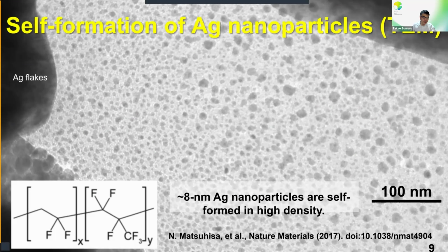So this view graph shows you the ink formulation. So we add the silver flake with a typical dimension of 2 to 3 micron among the fluorinated copolymer, adding the surfactant and organic solvent, mixing together, printing once and annealing at 150 degrees Celsius. So when we observe the cross-section of the printed elastic conductor, we eventually realize the silver nanoparticles are naturally formed and uniformly and densely dispersed among the rubber matrix.